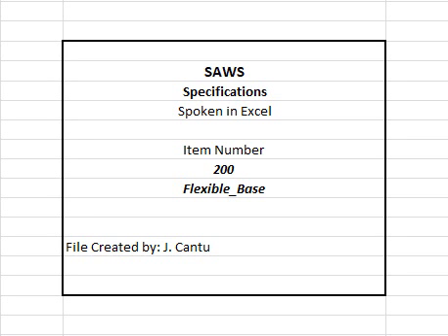200.5 Testing. Testing of flexible base materials shall be in accordance with the following TX-DOT standard laboratory test procedures. 1. Preparation for soil constants and sieve analysis Tex 101E. Liquid limit Tex 104E. Plastic limit Tex 105E. Plasticity index Tex 106E. Linear shrinkage Tex 107E. Sieve analysis Tex 110E. Los Angeles abrasion ASTM C131, Grade A. 2. Samples for testing the material shall be made available to the inspector and taken prior to the compaction operations.